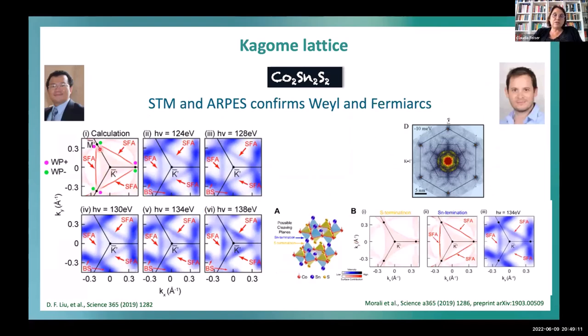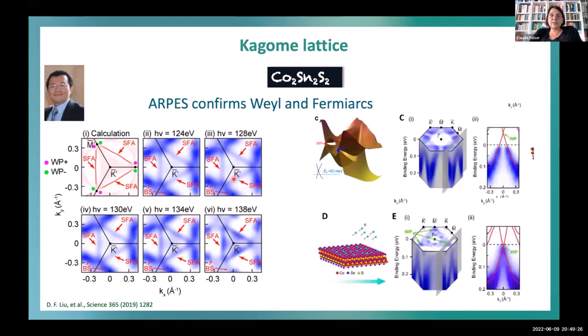But here also we could see, this is calculation versus measurement. And again, angle-resolved photoemission and also STM. We could nicely prove that this compound has very nice Fermi arcs in the surface electronic structure. And we see here on the side, if you don't have all the pictures there, that you have a nice Weyl crossing. So you have this linear dispersion in the electronic structure in this material. And the Weyl points are here slightly above the Fermi energy. So you have to dope it a little bit with potassium to see it then at the Fermi energy.